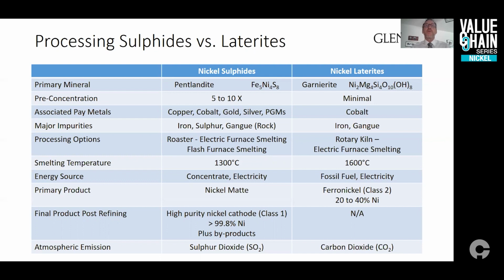Nickel sulfide deposits are commonly associated with a variety of additional pay metals. For example, in PGM deposits in South Africa, platinum and palladium are actually the primary metals, and nickel is considered the byproduct. In nickel laterite deposits, cobalt is the only other pay metal. However, since it is not easily separable during smelting, it is actually considered an impurity in the final product. The job of the smelter is to enrich the nickel content by eliminating impurities. In addition to the sulfur contained in sulfide ore, both ore types contain iron and inert rock known as gangue.